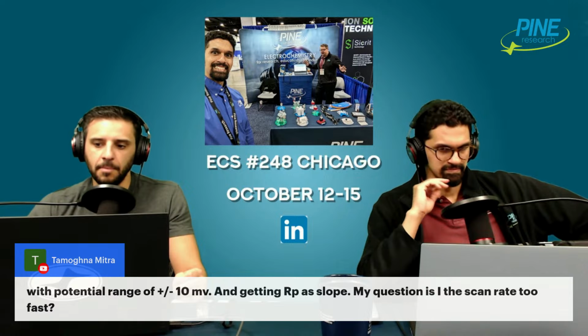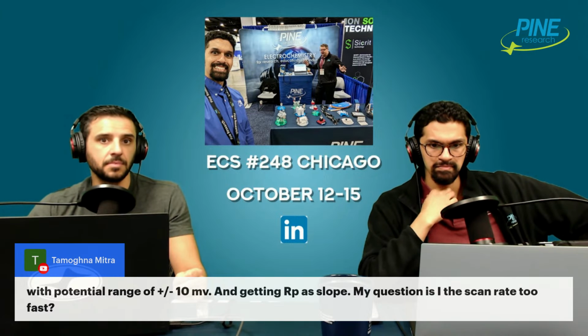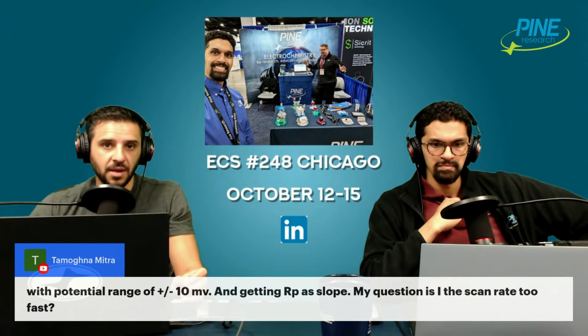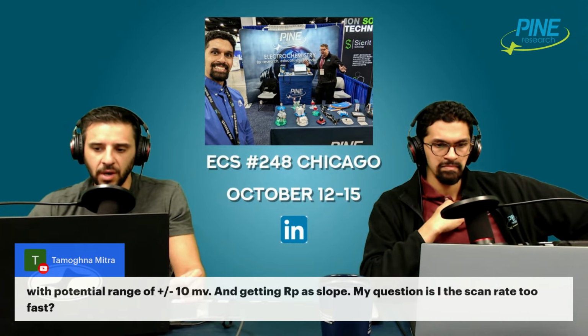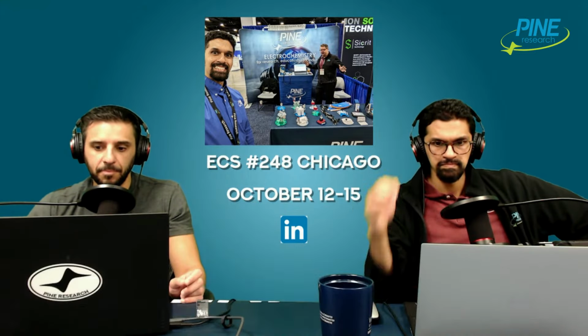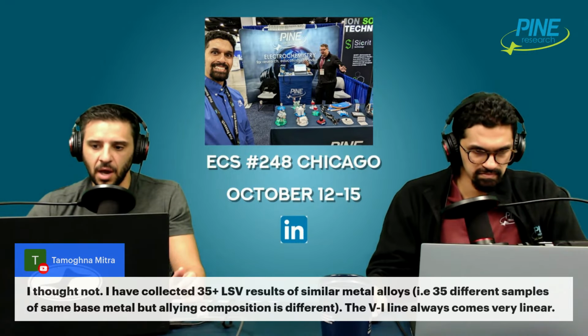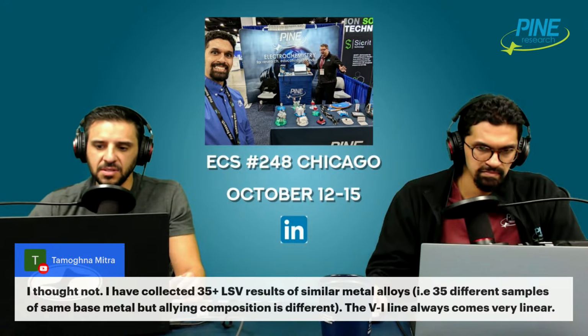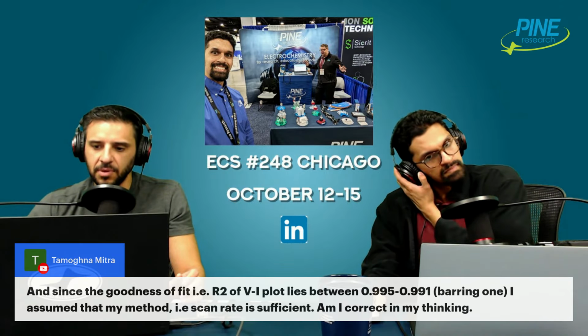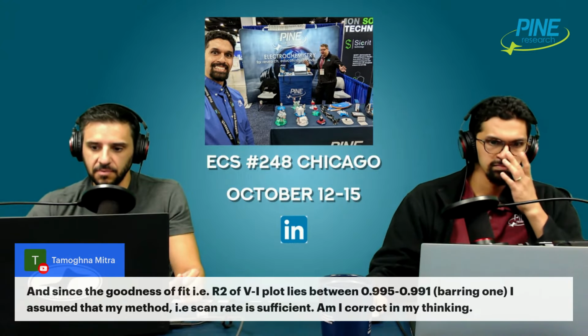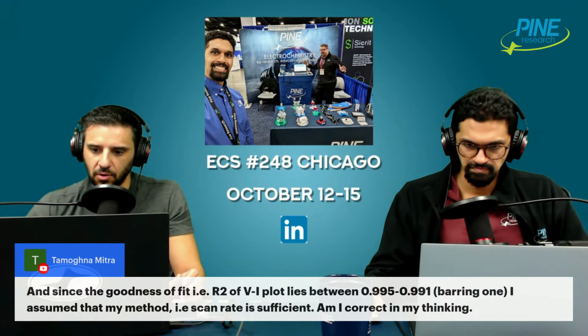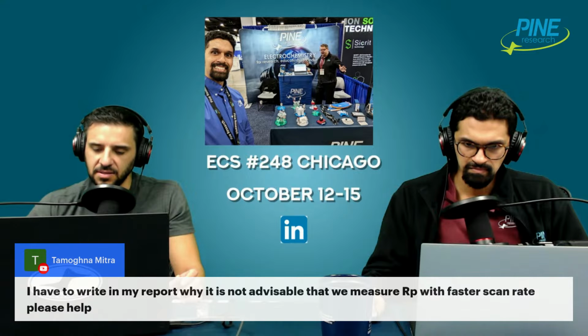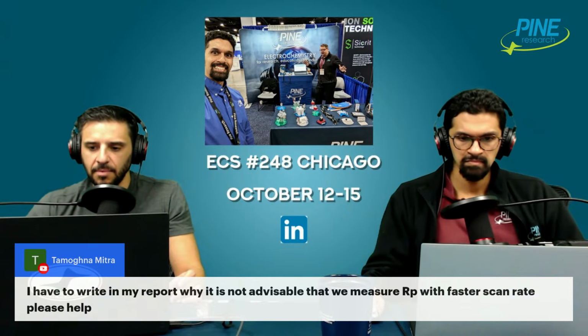Probably not. But what I would say is 1 millivolt per second is probably your maximum. As a general rule of thumb for polarization resistance measurements through scan, like sweeping potentials, you're going to want to be somewhere between 0.1 and 1 millivolt per second. So 1 millivolt per second might be the fastest you would want to go. But to your point, your follow-up statements were, I thought, not. I've collected 35 plus LSV results of similar metal alloys. The VI line always comes very linear. And since the goodness of fit, which is the R squared of the VI plot, is between 0.995 and 0.991, so very good, right? I assume my method, the scan rate is sufficient. Am I correct in thinking? I have to write in my report why it is not advisable that we measure RP with faster scan rate. Please help. Yeah, you are correct in your thinking.